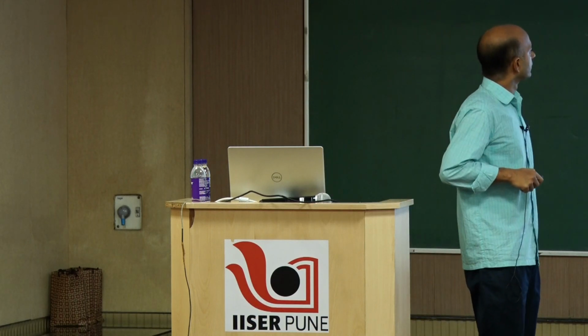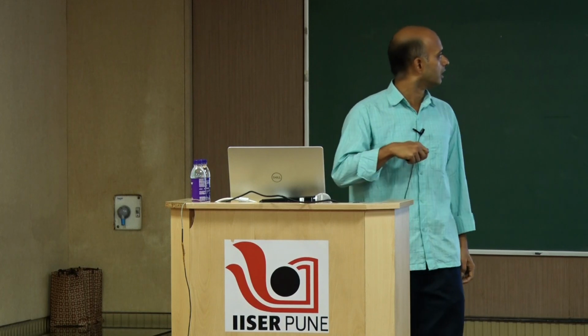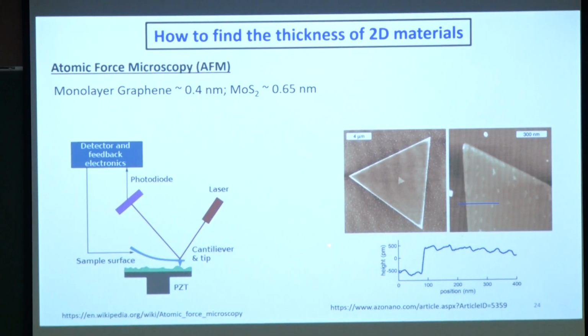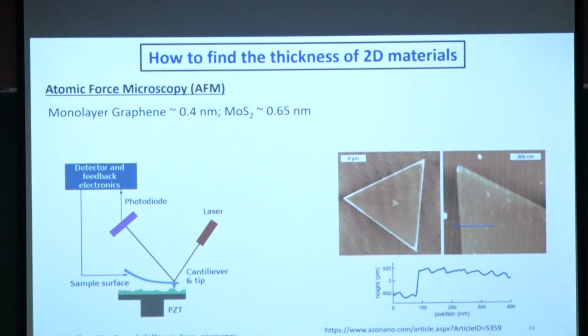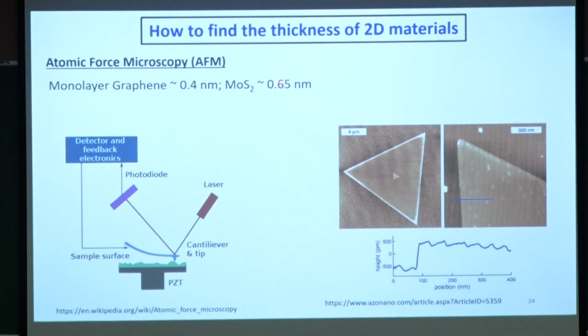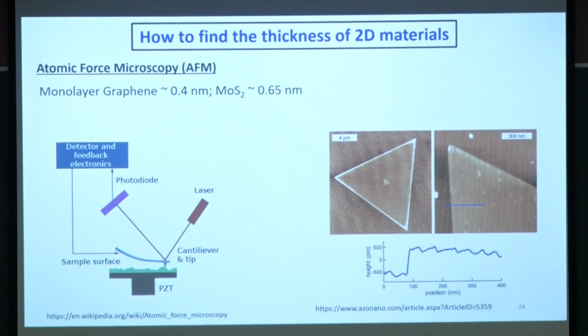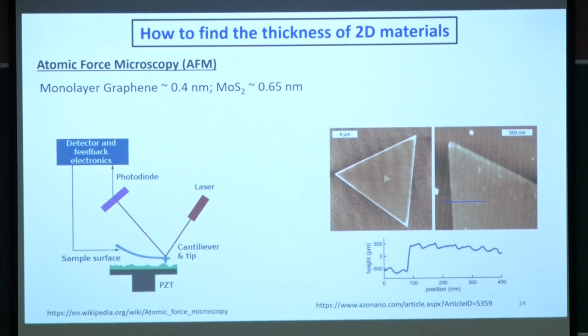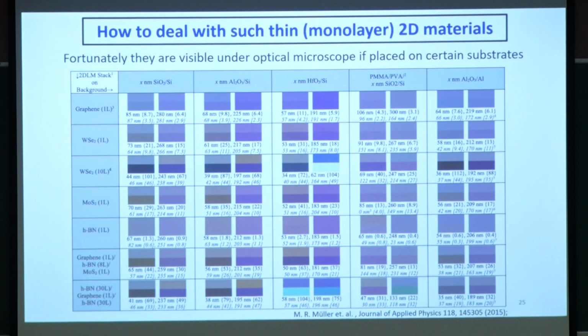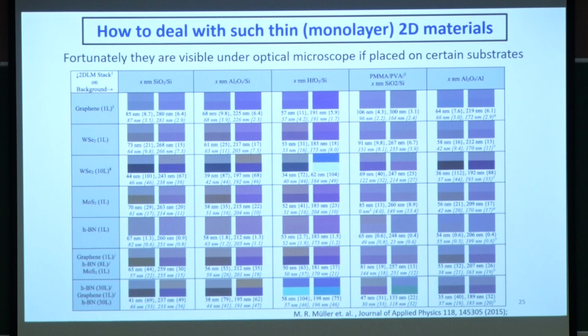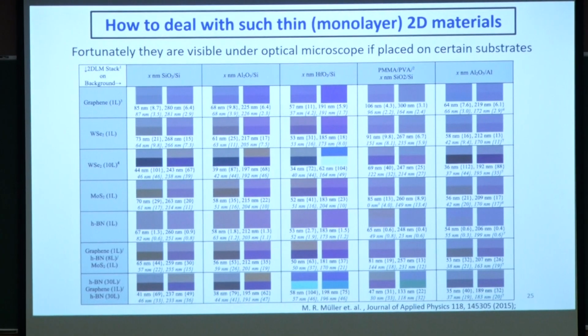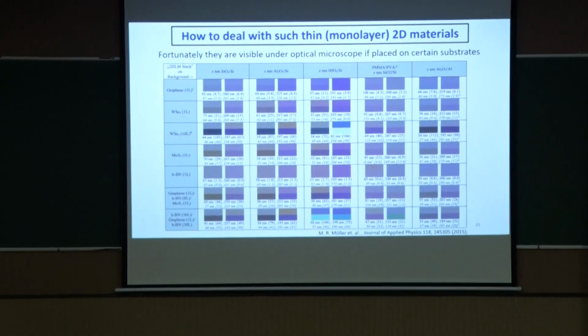The next technique you can use to identify the thickness is atomic force microscopy. If you have the machine, you can use it and find the thickness of a monolayer. For graphene it is 0.4 nanometer, and MoS2 is around 0.65 nanometer. This is how AFM works these days. But not everyone has access to it, and it is not always easy. You might have a long queue to use one of these instruments to figure out whether you got a monolayer or not, but you want it all the time.